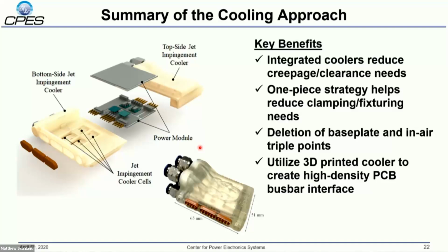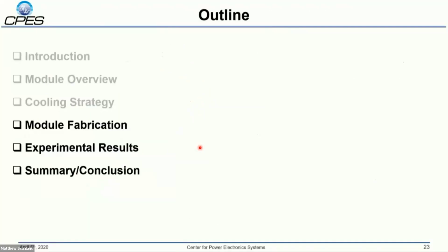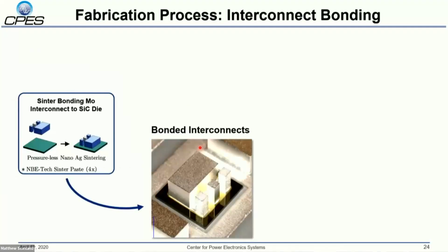So, a summary of some of the ideas I've talked about here. Some of the key benefits of this approach are we've integrated the coolers, which reduce the creepage and clearance needs. We've also moved to a one-piece housing strategy, which should help us reduce some of the clamping and fixturing needs. We've managed to delete the base plate and also remove these in-air triple points. So we keep all those really critical insulation points inside the encapsulant, but without taking on the overhead of the base plate. And we can also utilize this 3D printed cooler to create a high density PCB bus bar interface. So last, I'll touch quickly on some module fabrication steps.